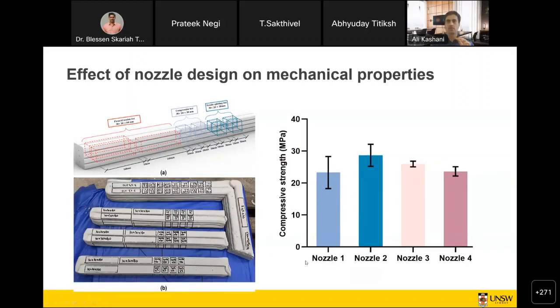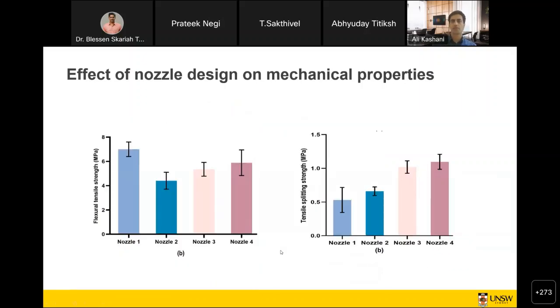We printed some small samples, and then we cut the samples to measure flexural strength, compressive strength, and tensile strength. As you can see, based on the type of the nozzle that we use, the compressive strengths might be changing. So you can see nozzle 2, which is the square nozzle, gives us the highest compressive strength. But it's also different in terms of flexural strengths and tensile splitting strengths.